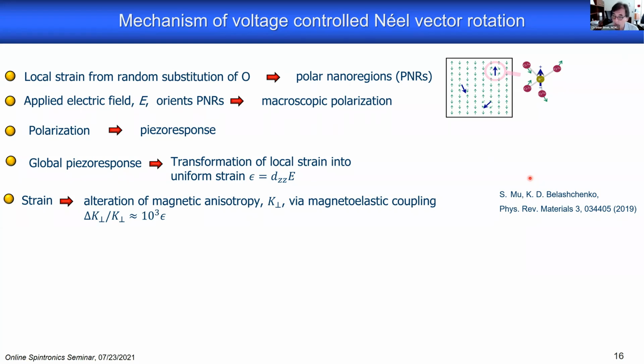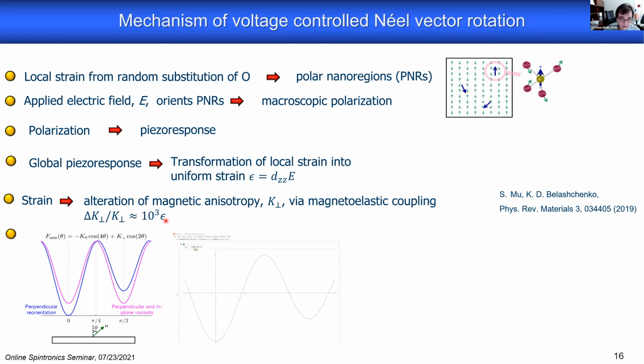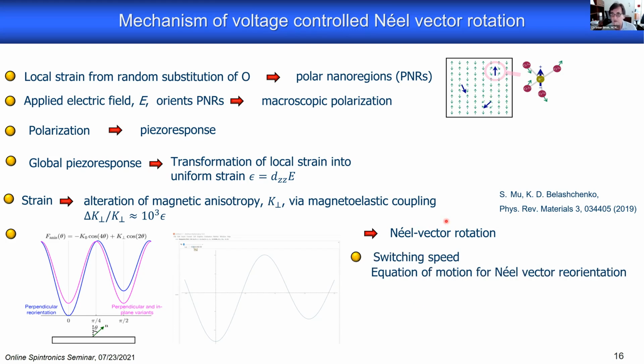Granted, okay. So based on that, we assume anisotropy. By the way, it's worth mentioning also, you can read this in the paper, that the anisotropy of pure chromia is already quite weak. So it doesn't take much to change that. And then we think that the change in strain changes the anisotropy. The change in anisotropy changes the landscape of the anisotropy free energy and allows switching between different local minima, and that gives rise to the Néel vector rotation, not switch, by 90 degrees.